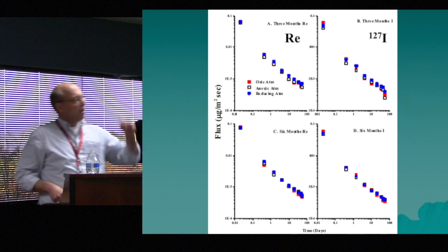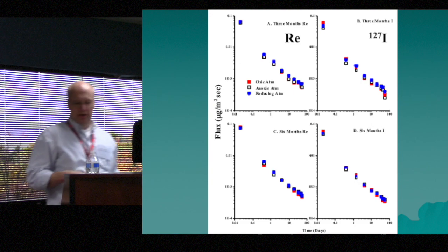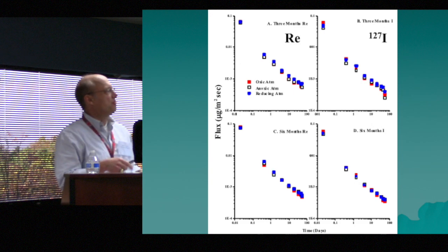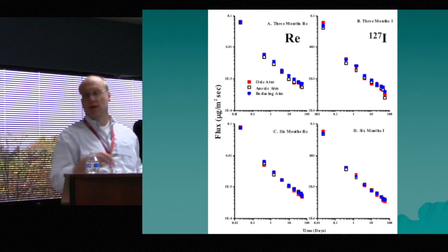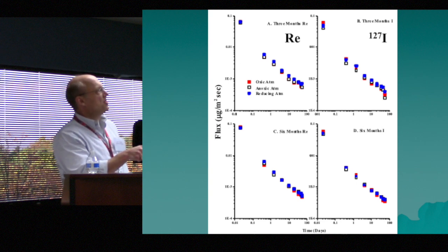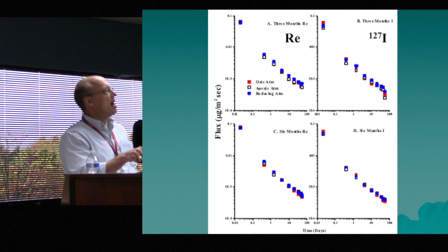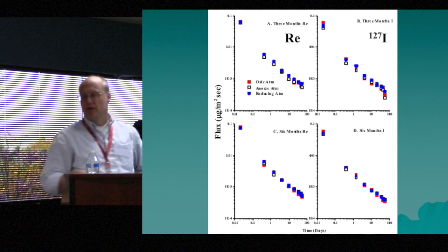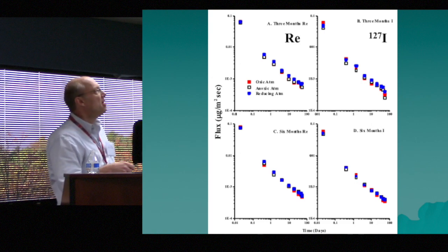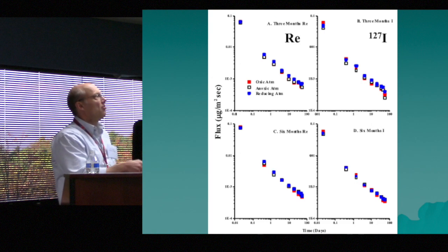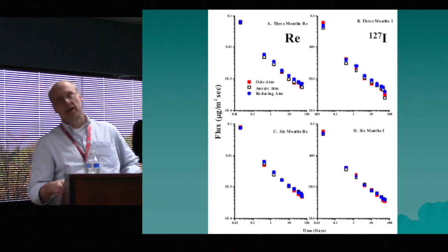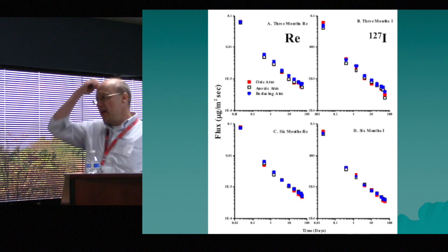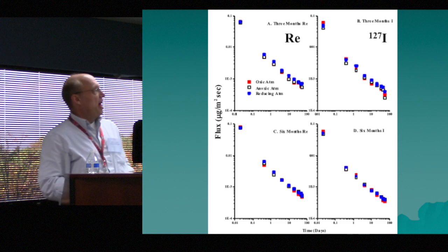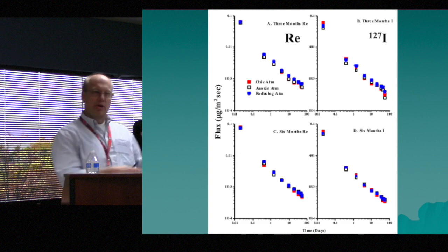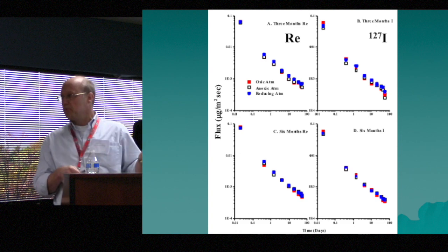So if you actually plot the 63-day data on a log plot, and this is data for rhenium and data for iodine-127, what you see is you should get this decreasing flux over time, and on a log plot, it should have a slope of -0.5. And what that says is that you can kind of use this way to interpret the data.